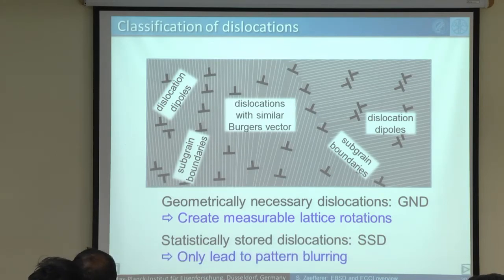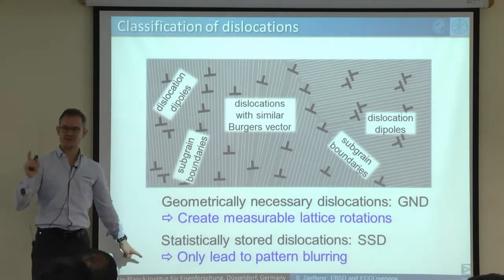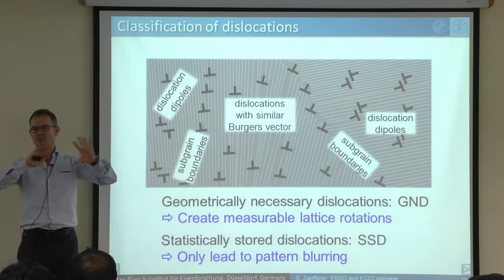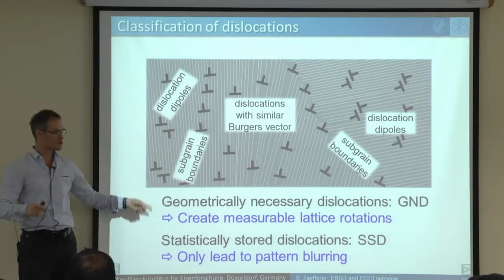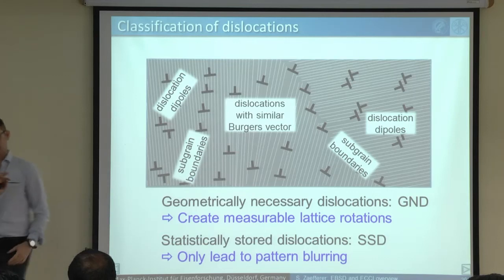So as SSDs, you can see them with EBSD, but they only lead to a blurring of the diffraction pattern, but not to measurable rotations. Okay, so this is important: the dislocations themselves are not different. This dislocation is not different from this one, but the arrangement is different. These ones are in dipoles, and these ones are monopoles.